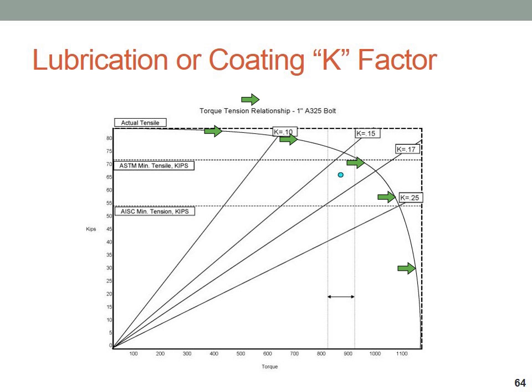What I mean by that is with an effective lubricant like that 0.10, we can develop almost all of the tensile strength of the fastener because there's no twisting motion being applied to the threads at the same time that they're being pulled. In a more typical range, like the 0.15 to 0.17, we actually lose quite a bit of the bolt's capacity to torsional twisting, or those torsional forces that are being applied at the same time. At a really high K factor of 0.25, it may actually be impossible to reach minimum fastener tension before we twist the bolt off in torsion. And that's why that 0.25 is established by the Federal Highway as a maximum K factor for their bridge and highway work.